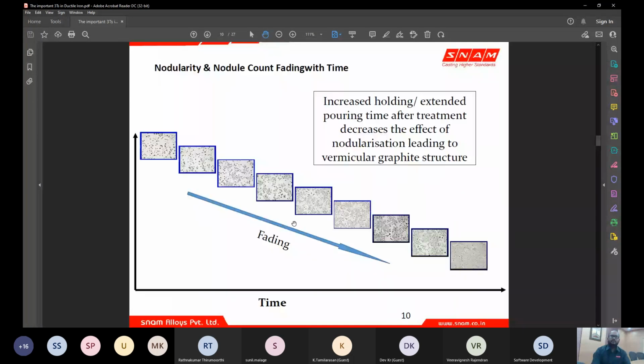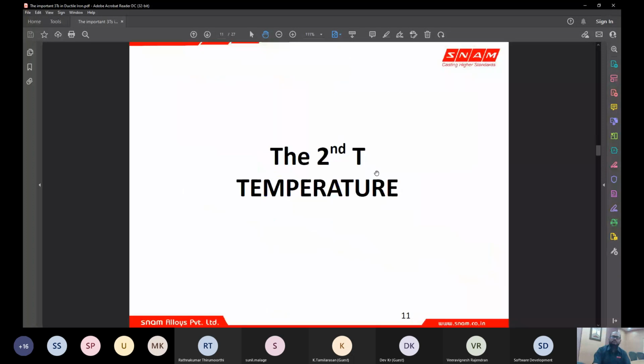So this is again a graphical or microstructure representation of how fading happens with time. Increasing holding or extended pouring time after treatment decreases the effect of nodulization, which leads to vermicular graphite, which is not desirable, or not accepted, in ductile iron production. So we'll be going into the second T, which is temperature.